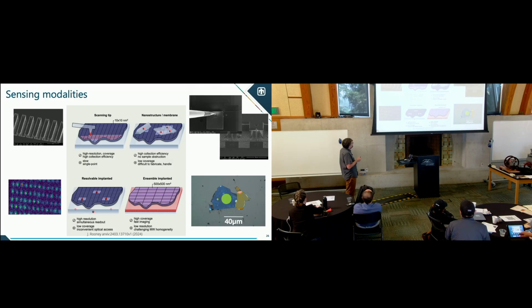So scanning NV AFM is actually a really cool technique which gets you the highest magnetic resolution of any sensor that I know of. What that is, is you have this cantilever on a tuning fork AFM with a single NV on the tip. You're optically addressing this single NV, but you're moving things under it with nanometer precision. So you'll see changes in magnetic field based on the position of your sample under this, and that allows you to actually defeat the diffraction limit of light. So typically your magnetic sensitivity spatially, if you don't have such an instrument, is limited by the diffraction limit of your laser beam coming in. And for visible light and a 100x objective, that's typically about 400 nanometers.